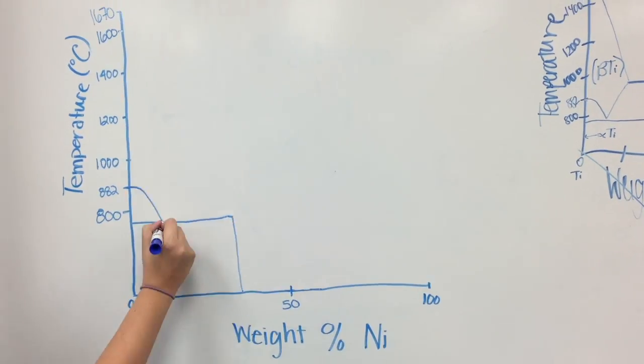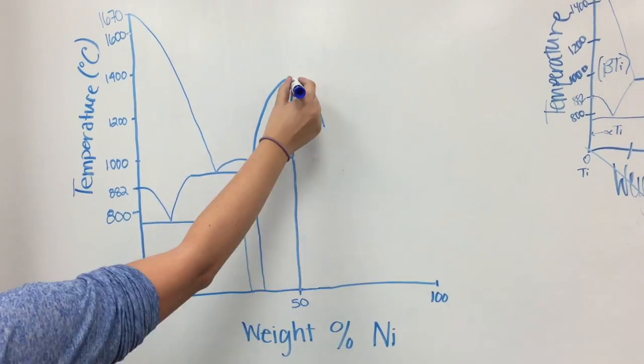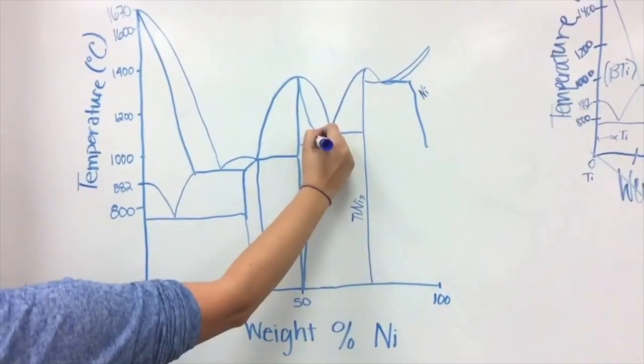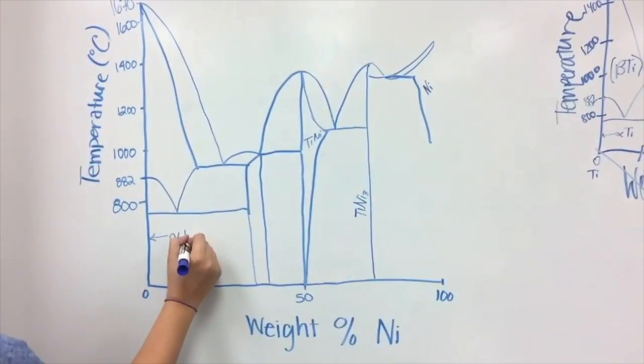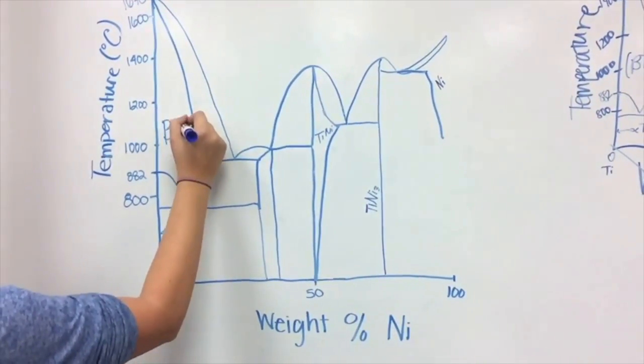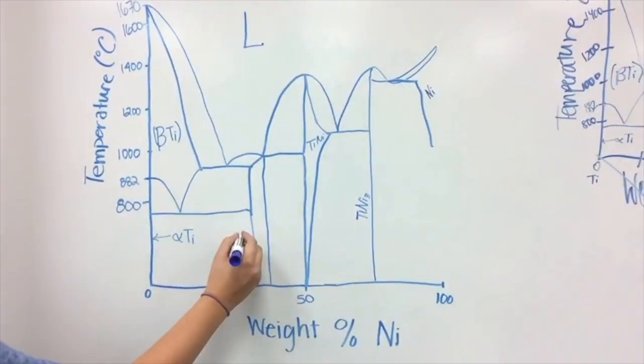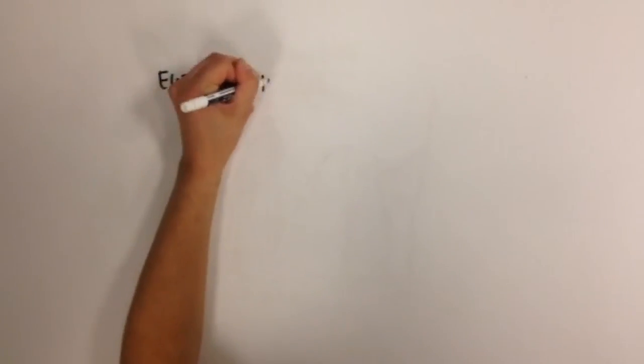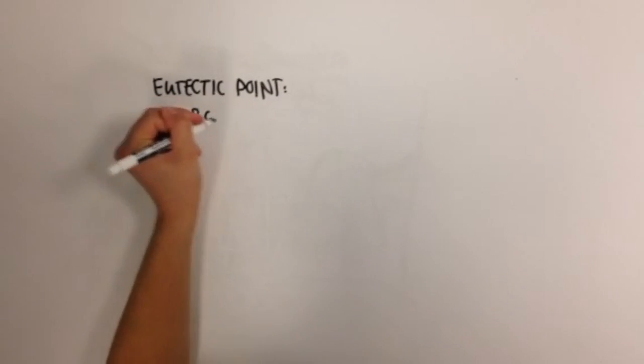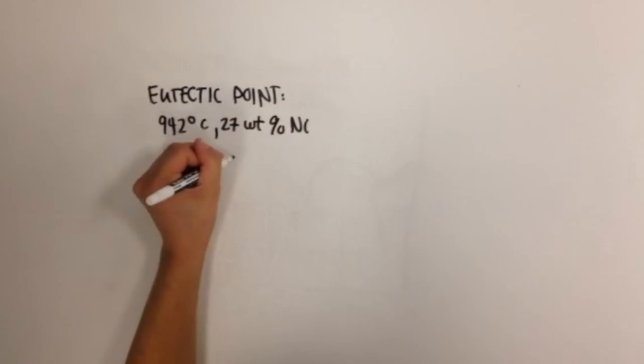One is a temperature of 942 degrees Celsius and 27 weight% nickel and involves a transformation from liquid to beta titanium and Ti2Ni. The other is at a temperature of 1118 degrees Celsius and 65% weight nickel and involves a transformation from liquid to TiNi and TiNi3. The microstructures of compounds directly under the eutectic point will form lamellae, in which beta titanium and Ti2Ni form in